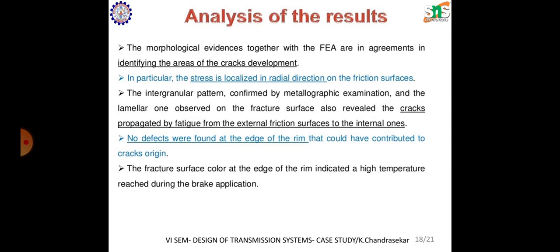Analysis of the results. The morphological evidence together with the FEA are in agreement in identifying the area of crack development. In particular, the stress is localized in the radial direction on the friction surface. The intergranular pattern confirmed by metallographic examination and the lamellar one observed on the fracture surface also revealed that the cracks propagated by fatigue from the external friction surface to the internal ones. No defects were found at the edge of the rim that could have contributed to the crack origin. The fracture surface color at the edge of the rim indicates a high temperature reached during the brake application.